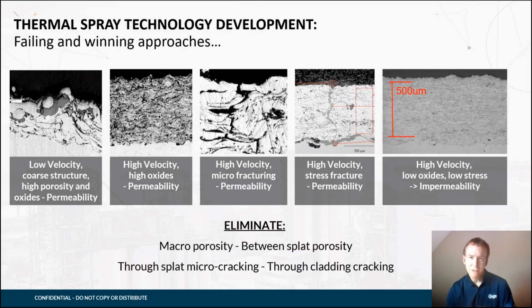So we have to use a system where the conveyance or the application equipment is specifically designed to install a very dense microstructure. So we eliminate these potential pathways to the substrate from a microstructural perspective, and we need to use a modified alloy. And the modification is to increase, for example, some of the alloy composition so that the oxidation that takes place during application doesn't affect the performance of that alloy in the environment. And we have to de-stress the applied system to avoid the issues with cracking, whether that's macro cracking or micro cracking, which would create pathways to the substrate.